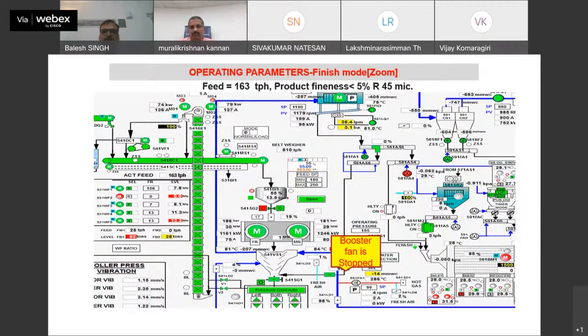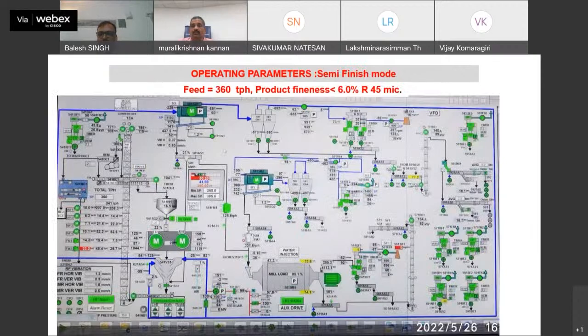But recently I have collected some more plant data, which is nearby this plant. So this is one recent screenshot. You can see it is yesterday's screenshot, where one 4.6 meter diameter ball mill is connected with RP16, the same RP, which has a 1450 kilowatt motor. This altogether is operating at 360 tons per hour, and this 360 tons per hour is all the ratio mix. The raw mix is the same, meaning clinker, gypsum, limestone, fly ash, slag. All together these are working, and at this level the product fineness is less than 6%, and the total power for this circuit is coming to 24 to 25 kilowatt per ton.